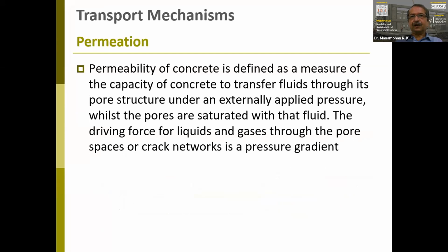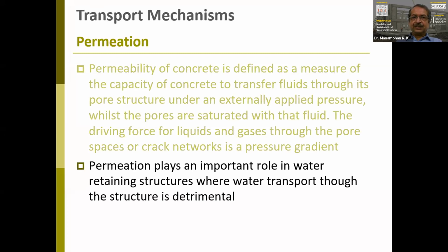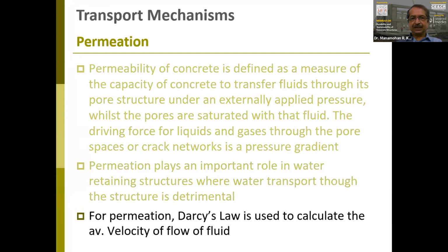Permeation or permeability of concrete is defined as a measure of the capacity of concrete to transfer fluids through its pore structure under externally applied pressure. That's very important: when we talk of permeability, we talk of an externally applied pressure under which this fluid transfer takes place, while the pores are saturated with that particular fluid. The driving force for liquids and gases through the pore spaces or crack network is a pressure gradient. The permeation plays an important role in water retaining structures where water transport through the structure is detrimental. And for permeation, Darcy's law is used.